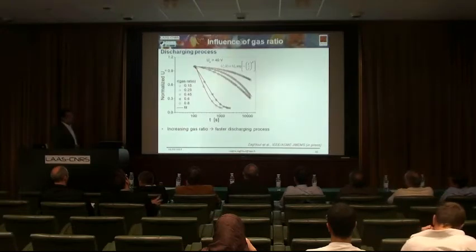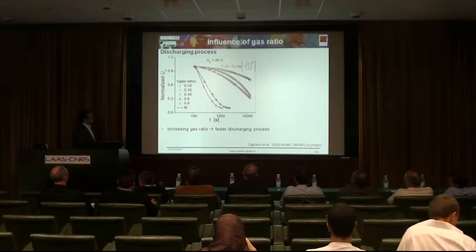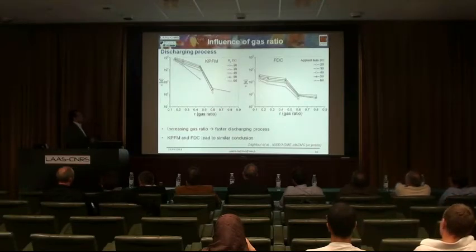When we go for the decay, we find also the same. The decay time constant is decreasing when you increase the gas ratio, and then a sudden drop here at these 2 points, confirmed actually by the decay time constant. This is a logarithmic scale, so you have to be careful about treating this graph, and the same stuff from